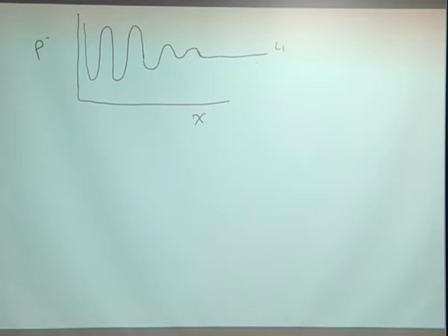So you have the liquid out here, you have the solid back here. If you start from this liquid and you want to create the Fourier components necessary to reconstruct the crystal, you'll find that you need an infinite number of order parameters, not just one. So you're absolutely right. That's kind of a theorem in the statistical mechanics community.